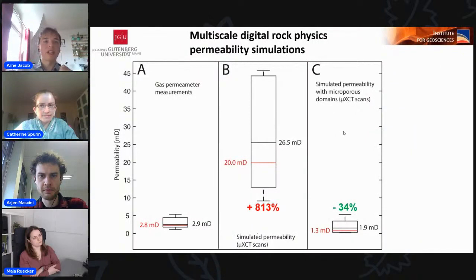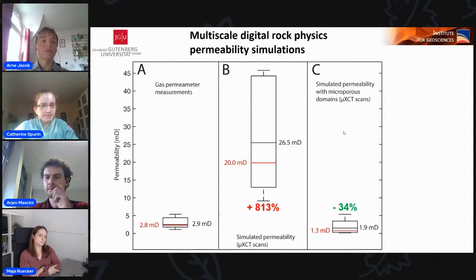So this is the main figure from our last publication. You can see on the left side that the range of values for the gas permeation test experiments is around 1 to 5 millidarcies. In the middle, there are the simulated permeabilities based on the original CT images of the samples. On the right side, you can see how the range of values changes when we model Brinkman domains, which contain the permeability information of the illite meshworks, into our samples. The black lines show the mean values and the red lines the median values. This figure illustrates how inaccurate the calculations would be without including the clay permeability of the illites into the scans.